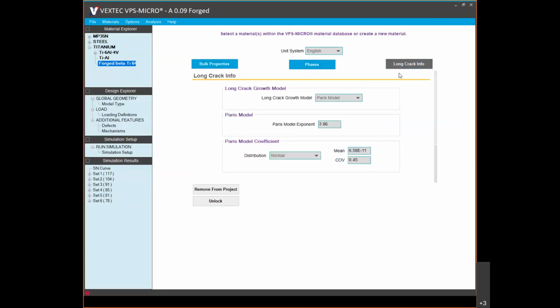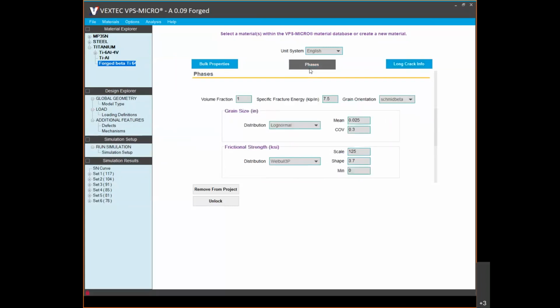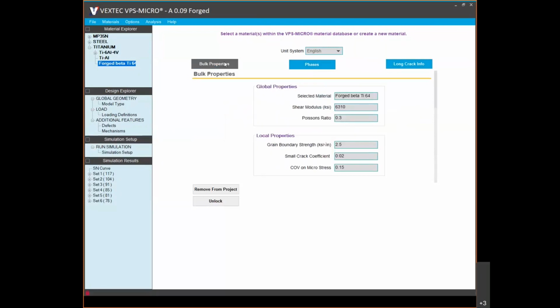And all of the dozen or so material property inputs that you see here are accumulated through standard ASTM type tests like metallography, tensile testing, fatigue crack growth testing. And the material parameters you see here are for our forged beta Ti-6-4 specimen.